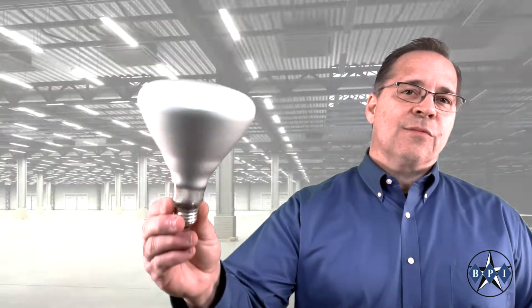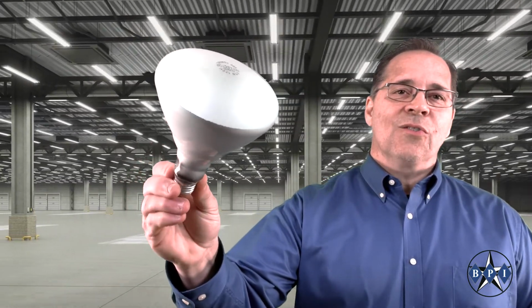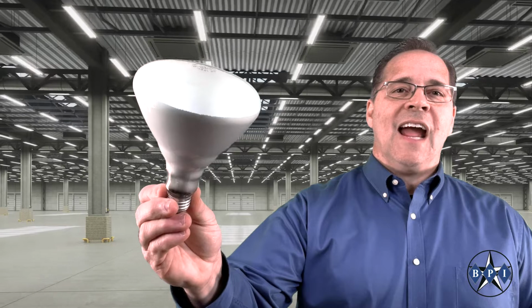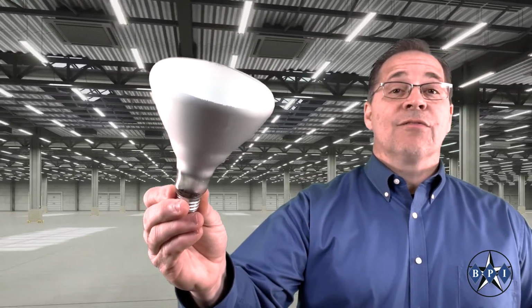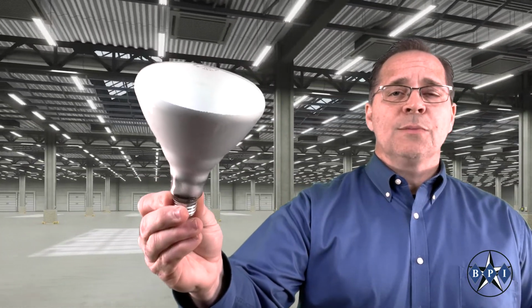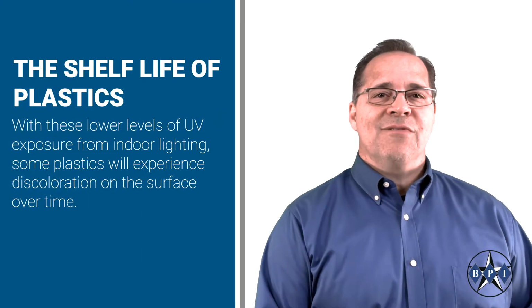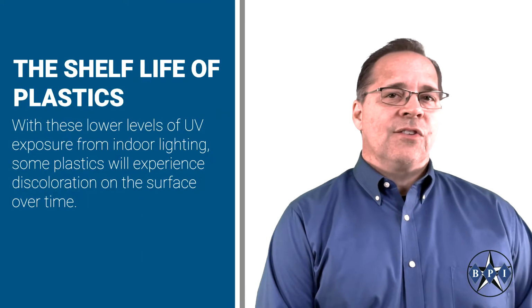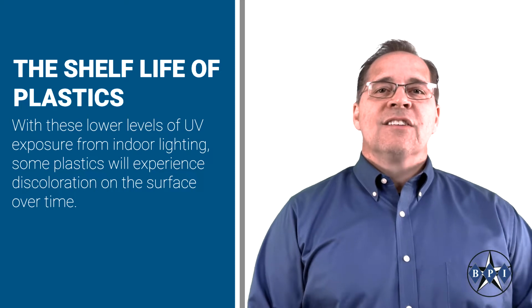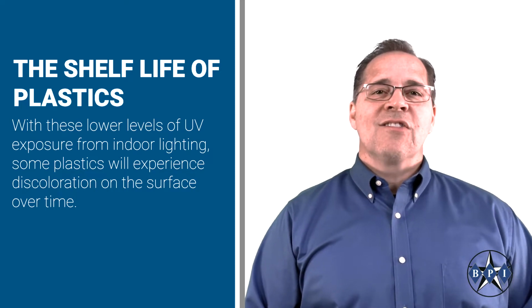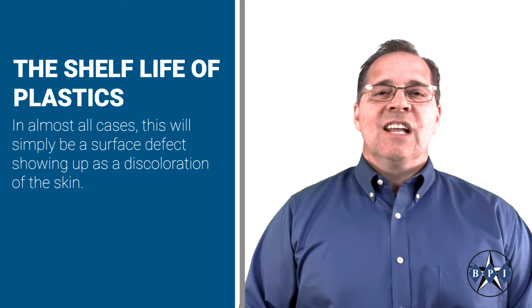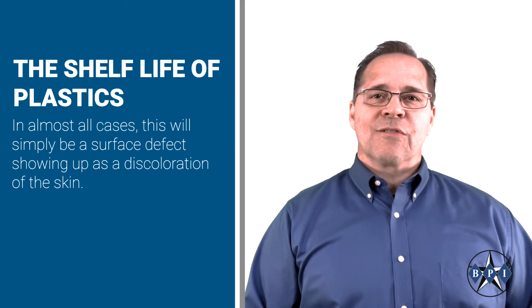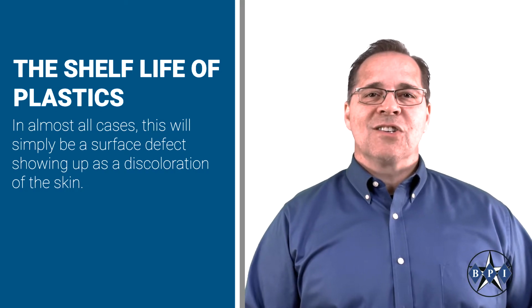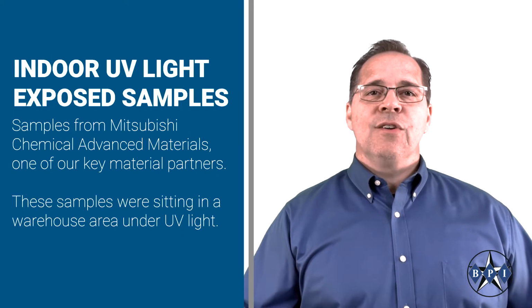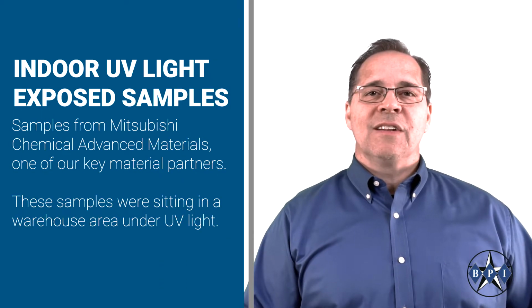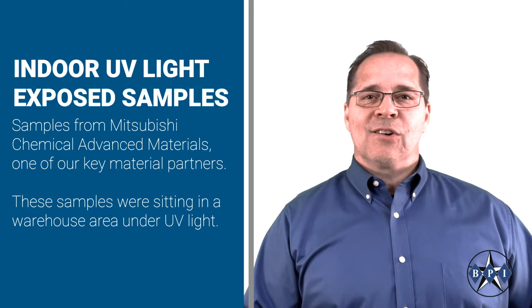Of course, UV exposure can also occur indoors. Commonly used indoor lighting, including halogen, incandescent, and fluorescent lights, will emit appreciable levels of UV light that can also have an effect. With these lower levels of UV exposure from indoor lighting, some plastics will experience discoloration on the surface over time. In almost all cases, this will simply be a surface defect showing up as a discoloration of the skin. I obtained a few small samples from Mitsubishi Chemical Advanced Materials, one of our key material partners.